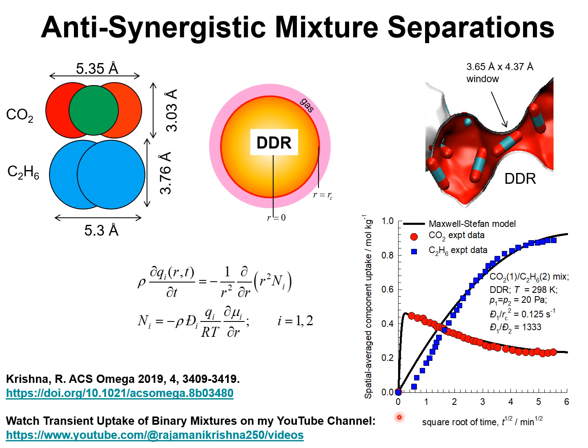Let's look at experimental data on transient uptake within crystals of DDR zeolite. The experimental data are shown by the symbols. The red circles are for CO2, and the blue squares are for the uptake of C2H6. At equilibrium, the loading of C2H6 is significantly larger than that of CO2. However, if you look at the initial transients, we note that the CO2 loading within the DDR crystals is significantly higher.